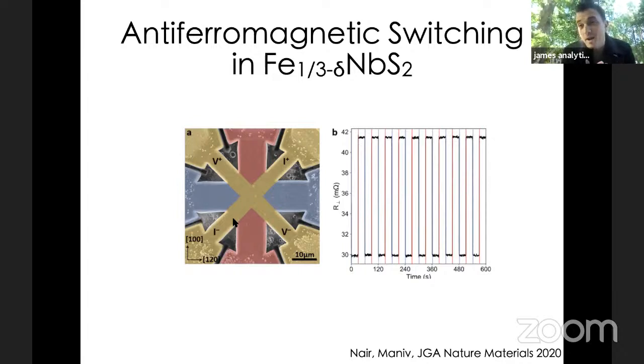We made this not by thin film or lithographic techniques, but actually using focused ion beam. So we took a single crystal, made a lamella, and machined out these little arrows, and then basically copied the same configuration that Wadley and others used in their 2016 paper, but now did it on a single crystal, because we didn't have thin films of this material.